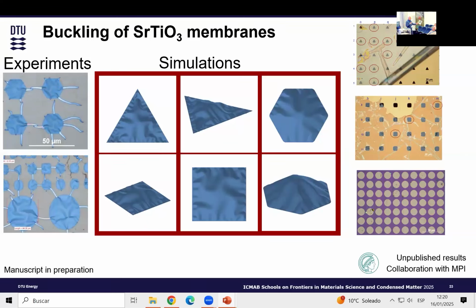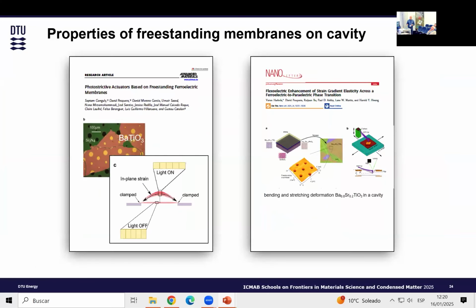So there is a critical thickness, we think, and we are working on it currently. There is a critical thickness below which the material is still flat. Maybe it's because of the material itself, and we are now trying to look at different materials and different thicknesses, to see what parameters make this critical transition from being buckled to being flat. Maybe people have observed it earlier, but we haven't seen any report on this. So for us, it was new that there is a critical thickness which causes it.